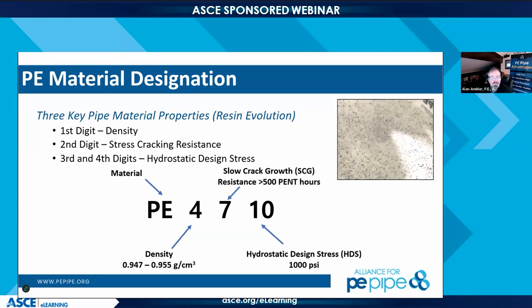But this 1,000 psi that we see here actually has a caveat already. It's already conservative in its function, because the ultimate tensile stress is 3,500 to 4,000 psi for HDPE pipe for the tensile yield. Is that correct? Correct. So what we're looking at, again, is the viscoelastic behavior and the effect of stress upon time.